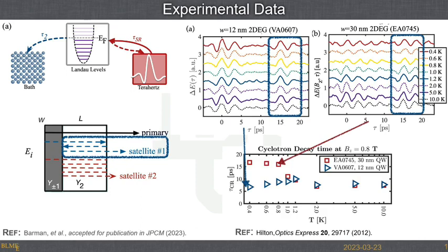And so I'm looking at a lifetime of about 15 picoseconds, which doesn't seem particularly long. But that's actually an extremely long period of time to be able to do these sorts of manipulations. That would be a quantum computer processor at something like 100 gigahertz on current scales. So it would be substantially faster than something that we've got available to us right now. But we'd actually be able to manipulate these materials on those sorts of timescales.